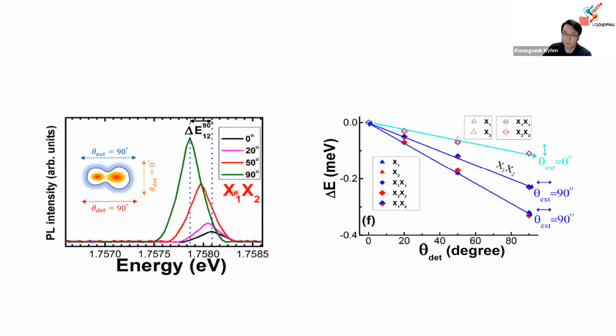And this is coupled biexciton, and it also shows a similar feature with the H polarized excitation. And we plot the energy difference from when the analyzed angle changed from 0 to 90 degrees. So it's analyzed angle and energy difference from here: 0, 20, 50, 90. So in the case of a 0 excitation, the spectral shift follows a linear trend.